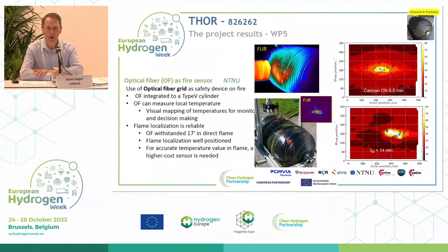Regarding the optical fiber embedded sensor to detect fire on the tank and open the pressure relief valve, the engineer has done a good job with embedded optical fiber in the tank. You can see on the picture that the localization of the flame was good, and the optical fiber withstood 17 minutes in a direct flame, which is enough to open the pressure relief valve. So it was a good result and interesting for us.